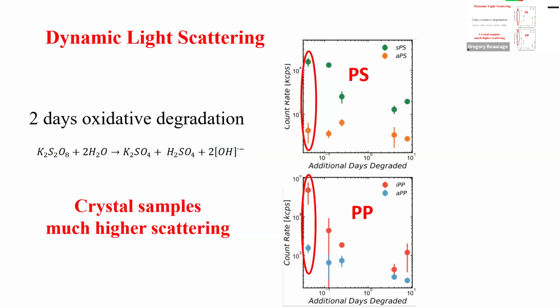Look at this one here. This is the semi-crystalline isotactic polypropylene. This is the atactic sample. The atactic sample scatters about 100 times less. So it tells you the atactic material, which doesn't have the lamellar structure, doesn't make a lot of micro- and nanoplastic, whereas the isotactic one does, and it's about 100 times more.